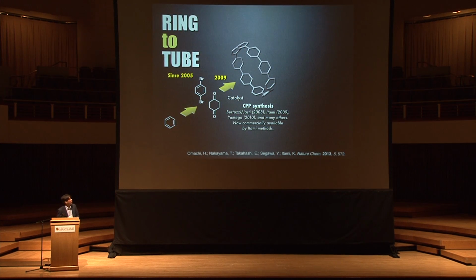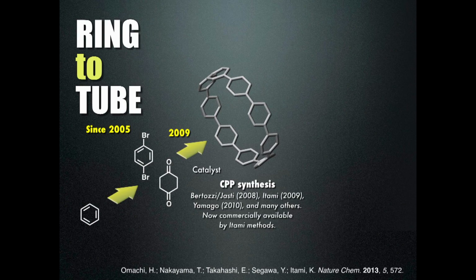For example, we're interested in making carbon nanotubes bottom up, since 2005 when I joined Nagoya University. Our strategy is very simple. First, make the shortest segment, that is the ring, and then grow them. It took us 4 years, but we were able to make these rings, cycloparaphenylene, by using the power of catalyst. I should also mention that we're not the only ones that achieved this. Professor Bertozzi, Jasti group, also Yamago group, and many others synthesize CPP these days. And now a range of CPPs became commercially available using our method.